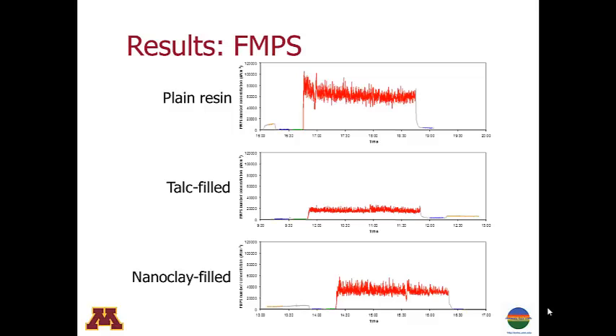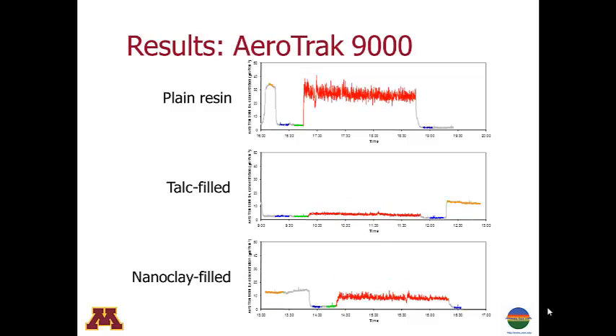Comparisons of the concentrations measured using the FMPS for the three types of plastic show the same ordering as we found with the P-track, with the plain polypropylene resin having the highest concentrations, followed by the nanocomposite resin, and then the conventional talc-filled resin. Looking at surface area concentrations, we see the same relationship among the different kinds of plastic, with the plain resin exhibiting the highest concentrations, the conventional plastic having the lowest, and the nanocomposite resin being in between.